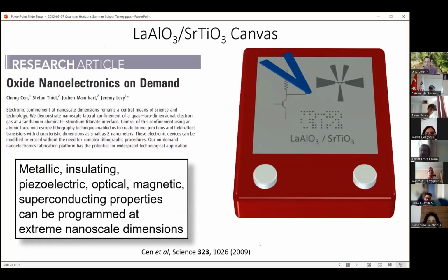And what we realized very quickly was that there was a lot of potential there. And really, the potential was not just because we were making small things, but because the material itself, this underlying material, strontium titanate, is a very rich physical system. It has a lot of rich properties that are tuned by this type of doping that is achieved with the AFM.